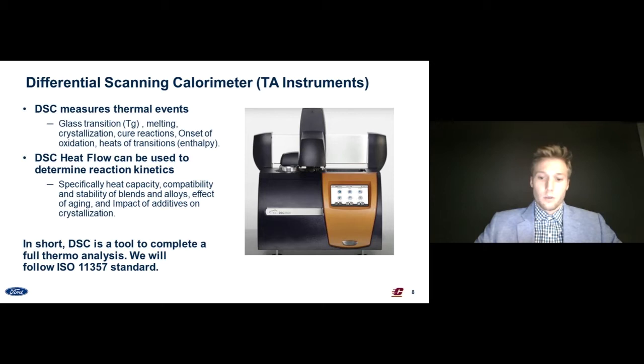A prevalent thermal analysis technique is the differential scanning calorimeter. The DSC measures thermal events such as glass transition, melting, crystallization, cure reactions, onset of oxidation, and heats of transitions, or enthalpy. The DSC heat flow can be used to determine reaction kinetics, specifically heat capacity, compatibility and stability of blends and alloys, effects of aging, and impact of additives on crystallization.